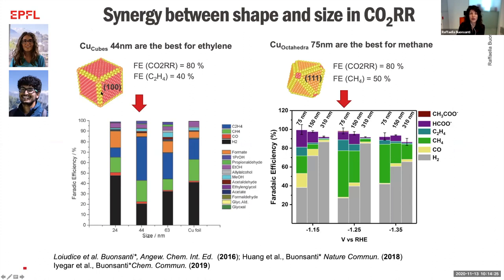Specifically, when we studied the cubes, in agreement with the single crystal studies, we did find that the 100 surface is more selective for ethylene, and the 111 surface is more selective for methane. However, we did find something special: the intermediate sizes are the most selective for CO2 reduction. Here I report the Faradaic efficiency versus the size. The Faradaic efficiency is a percentage and indicates how much of a certain product is produced. And here, this is ethylene. So the middle-sized cubes were producing a lot more ethylene compared to the others. And in the case of the octahedra, methane was produced up to 50%, again from these intermediate sizes.